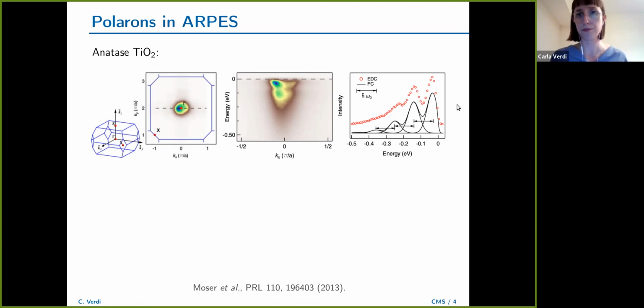And if you look at the energy distribution curve, so you cut this at the center, k equals 0, you see actually a series of peaks. So there is the first main peak and then satellites. Maybe I haven't used the word satellites yet. This is how people call this. And if you go into textbooks, you can see that this sort of feature can be attributed to the coupling of electrons to longitudinal optical phonons. Why? Because in particular, you can see that these peaks are equally spaced, and the spacing of the peaks is of the order of magnitude of the main longitudinal optical phonon energy.